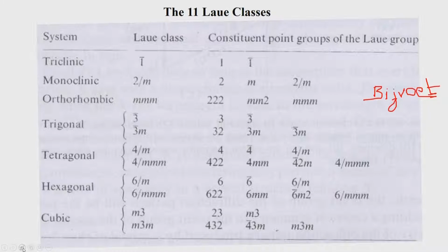So, when we discuss the structure determination protocol and the absolute configuration, at that particular time we will spend a little extra time to see how these Bijvoet differences, as they are called, the difference between I of HKL and I of H bar K bar L bar, are referred to as the Bijvoet differences. The presence of the Bijvoet differences can be utilized to determine the absolute structure of an organic molecule. In fact, it can also be used to determine the structures of large proteins,